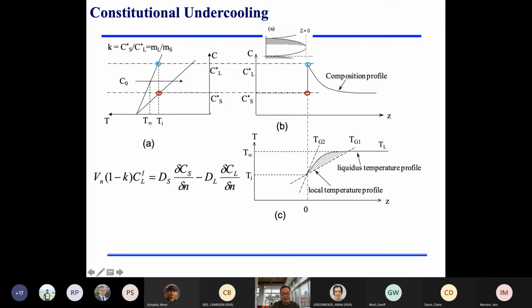But in most cases, we probably ignore the solid diffusion, because solid diffusion, Ds, is normally about 1,000 times lower than Dl. So essentially, the liquid diffusion controls, and then you have this kind of exponential decay of concentration profile. This will give you a liquidus temperature variation like that. This curve, we call a local liquidus temperature profile.